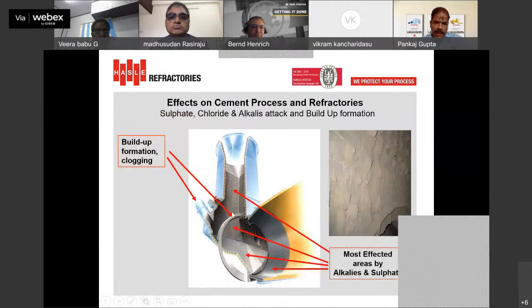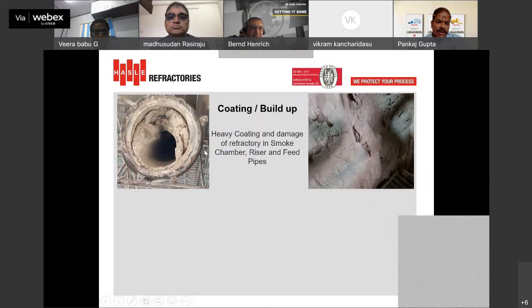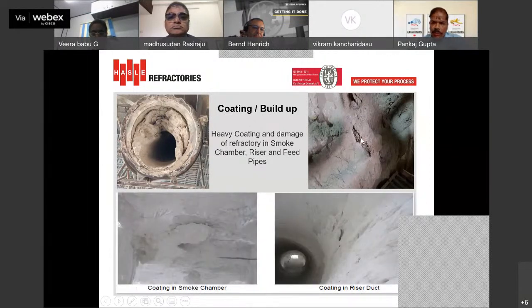Along with these chemical attacks, they also form a lot of acids which cause build-up and coating, especially in the preheater area, and more specifically in the riser area, feed pipes, and smoke chamber area. Here are a few pictures. This is the feed pipe, a picture from site, and you can see this feed pipe is around 60-70% filled with coating, and there is restriction in the flow of the raw material. And here is the picture from the riser where these acids stick to the refractory, and once this coating will be removed.